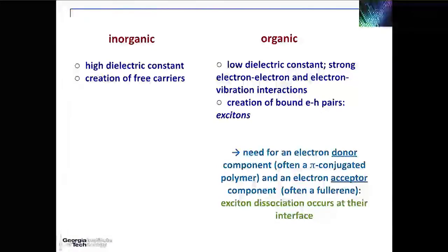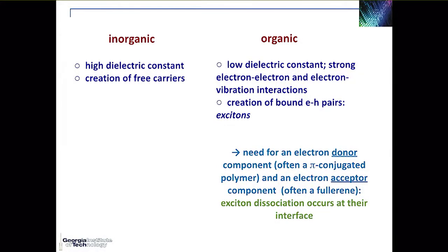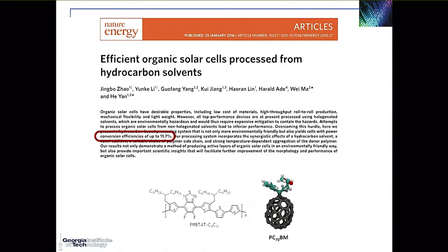Of course, if you have a bound electron-hole pair, there is no net charge that's created, and that's the reason why, in the case of organic solar cells, you need two components: an electron donor component, up to now very often a pi-conjugated polymer, and an electron acceptor component, up to now very often a fullerene derivative. And at the interface between those two components, that's where you get the possibility of exciton dissociation. Right now, in the case of polymer-fullerene solar cells, He Yan and coworkers, for instance, but there are also other folks